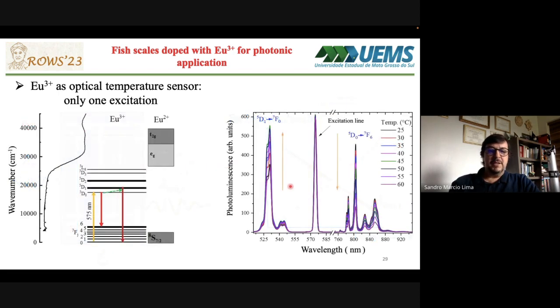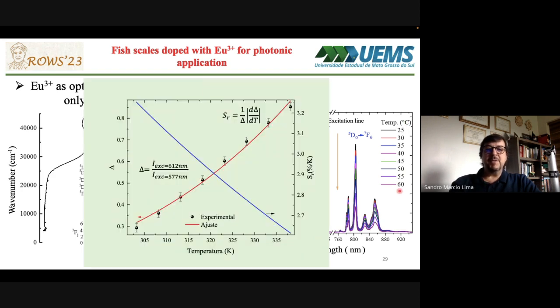In our case here, we excite the hydroxyapatite at 577 nanometers, and we observed these two regions here and here. We noted here an increase in this intensity, while we observed here a decrease in the intensity when the temperature of the sample changed from 25 Celsius degrees to 60 Celsius degrees. Performing the same calculation as before, we found a high relative sensitivity with a maximum of approximately 3.25% per Kelvin, which is very high when we compare with other europium systems in the literature.